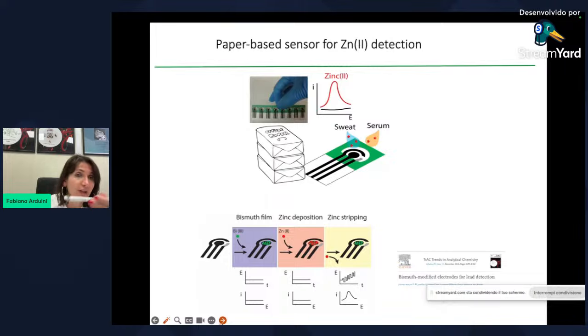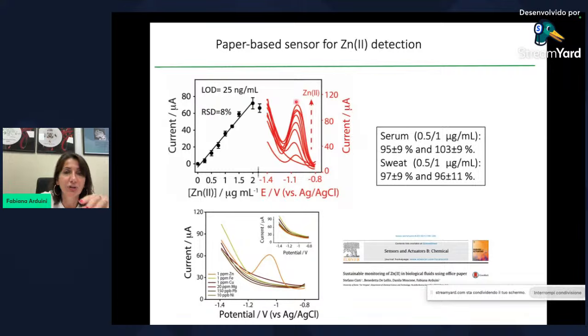In this case, instead of mercury, which is to be avoided for its toxicity, we selected the bismuth film. And so we have the accumulation of zinc ion close to the electrode, forming an alloy with the bismuth, and afterwards there is stripping analysis. In this case, we have the peak, and this is the calibration curve with a detection limit equal to 25 nanogram per milliliter. Afterwards, we also carried out the interference study, considering the working solution and the electrochemical parameters. We demonstrated that this sensor is able to detect zinc ions also in the presence of iron, copper, magnesium, lead, and nickel. And we also demonstrated the accuracy of this device by a recovery study using serum and sweat.